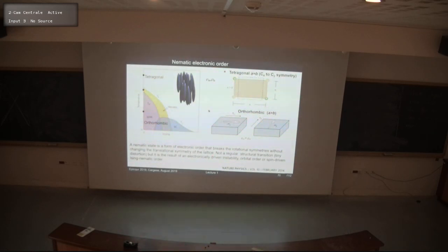So the question is always what determines this phase. It manifests by an extremely large anisotropy between the a and b axes, so already in the tetragonal system. So we know that something is happening to the system before it even enters this transition. But it can also have an origin coming from its susceptibility along this direction. So another thought is that it could be spin-driven Ising nematic order.